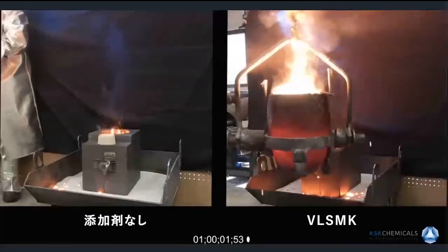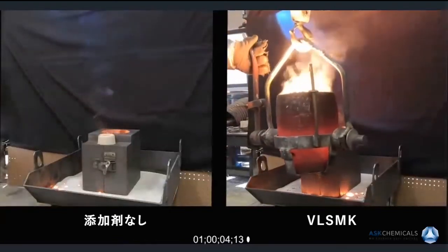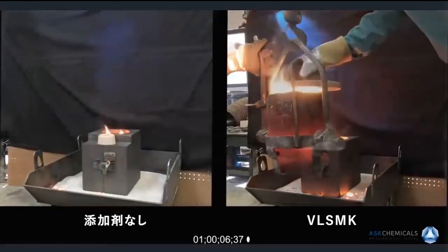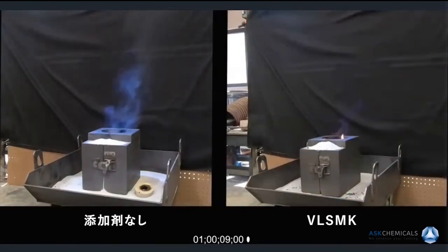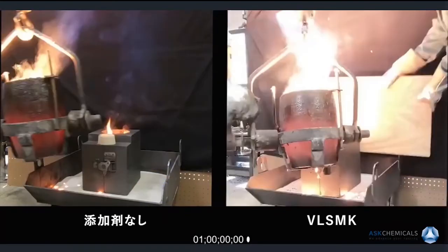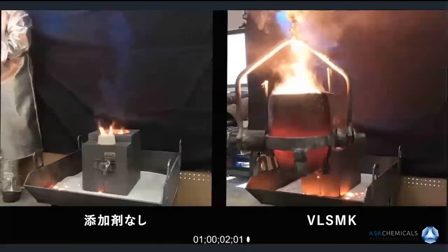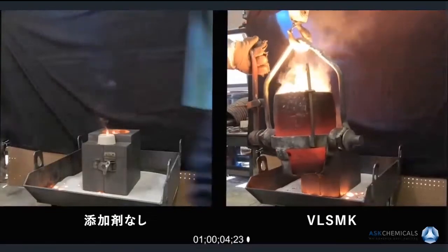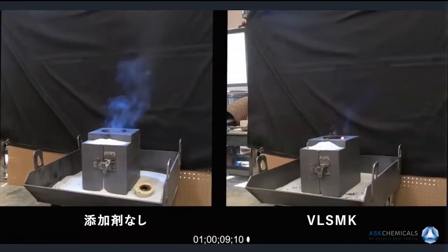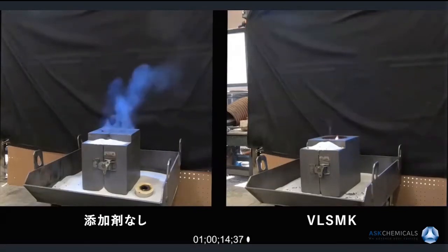So you can see here, I'm not playing the whole video because they're very long, because we were trying to set this up. On the left side, you see the no additive. And on the right side, you see the VLSMK engineered sand additive. I can play it again in case we went too fast. You can see on the left side, there's a significant amount of smoke when you don't have the additive. And once you place the additive in the core, you definitely suppress significantly the amount of smoke.